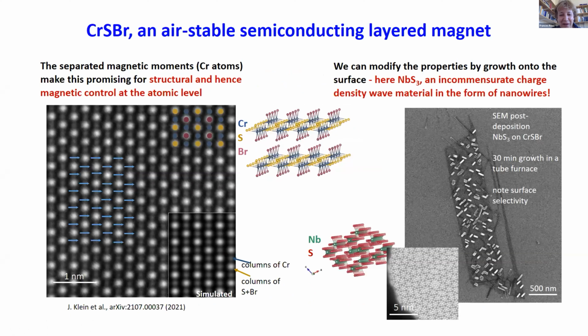All right, so the last one I'll show you actually is a completely different kind of material, a 2D magnet in which chromium atoms in the van der Waals sheets are lined up to make magnetic structure. And this has a very different symmetry. It has a rectangular unit cell, and we can grow other materials, like in this case, niobium trisulfide, onto the 2D CrSBr structure to get epitaxy.